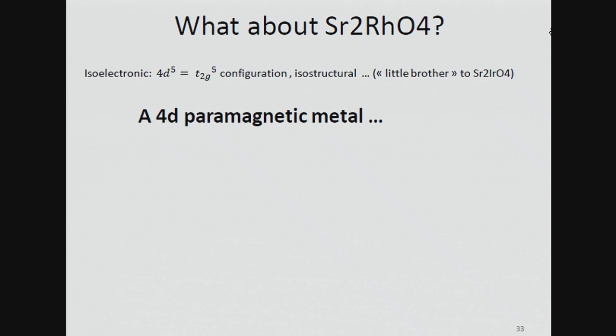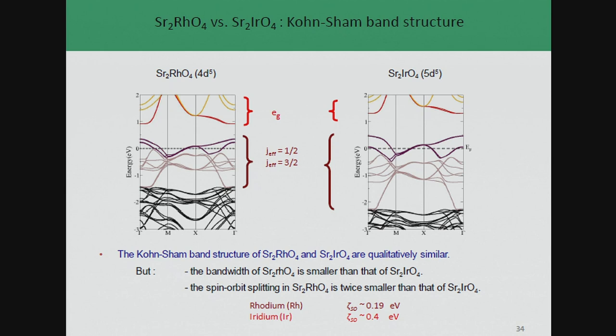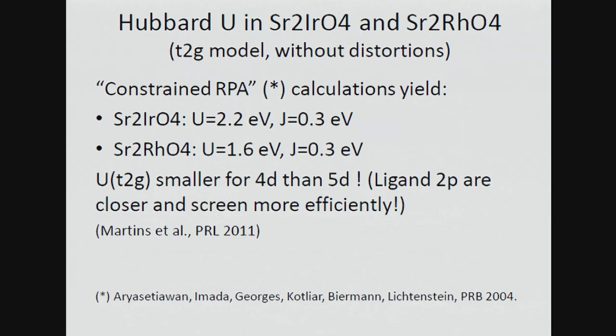We get the insulating state — but how? Let's look at the little brother: strontium rhodate. It is isostructural and isoelectronic, exactly the same thing apart from the fact that rhodium is a 4D transition metal, not a 5D one. The properties are completely different: strontium rhodate is a nice paramagnetic metal. As a sanity check, what happens if we apply our technique to that compound? Let's first do the DFT. If I look at the band structure, the T₂g manifold seems a bit more narrow than strontium iridate — that's worrying because you would think correlations are stronger here. However, spin-orbit splitting is smaller, so it's unclear.